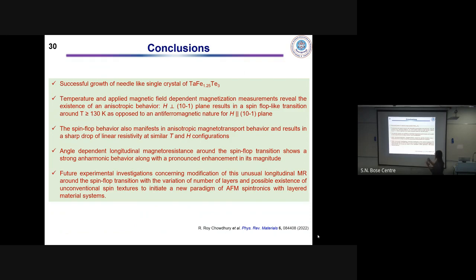It resulted in a spin flop-like transition at around T equal and above 130 Kelvin, as opposed to the antiferromagnetic nature when the magnetic field is in the plane of the sample. So this spin flop behavior also manifests in anisotropic magnetotransport behavior, and it results in a sharp drop of the longitudinal resistivity at similar T and H configurations.